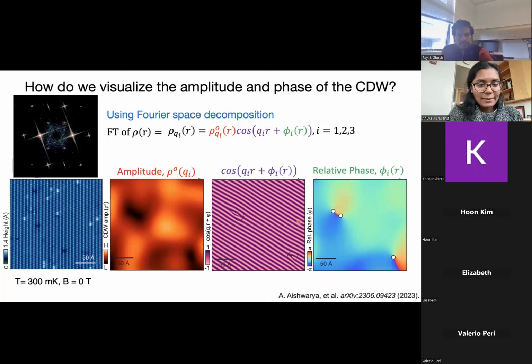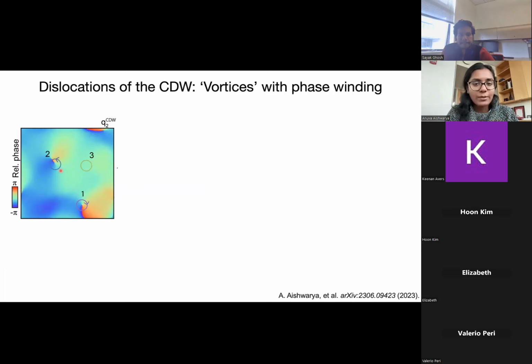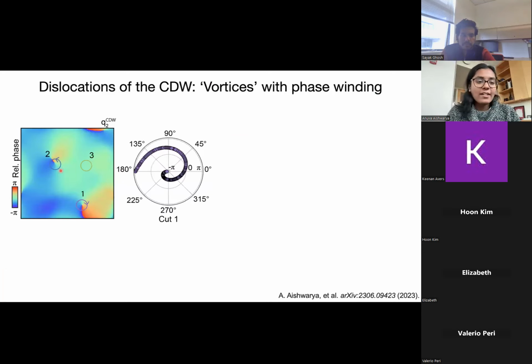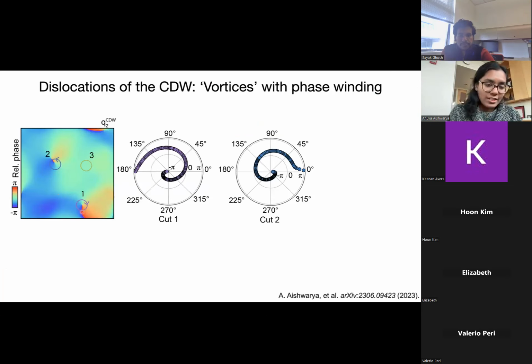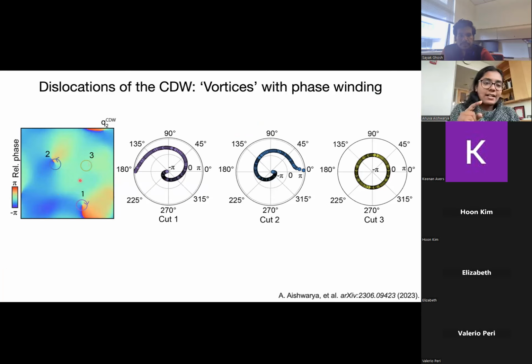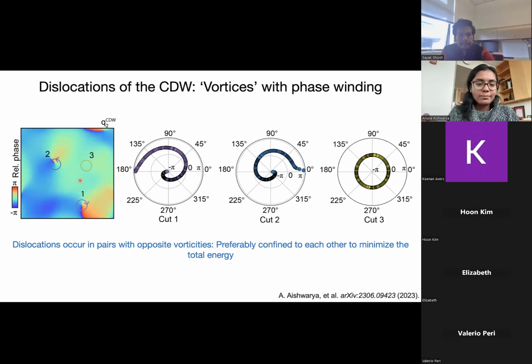So this is at 0 Tesla. And what we see are these phase windings, which are very few in number, even at 0 Tesla. If we take polar plots of that phase winding, and take a cut around one, you see that the phase winds from minus pi to pi, which is 2 pi. For the other one, it goes the other way. And if you take a region where the phase is pretty constant, we see a constant phase. These phase windings are opposite in nature, so they go by plus minus 2 pi, and we expect them to be confined to each other to minimize energy. So this is at 0 Tesla, where we do not expect a lot of vortices.